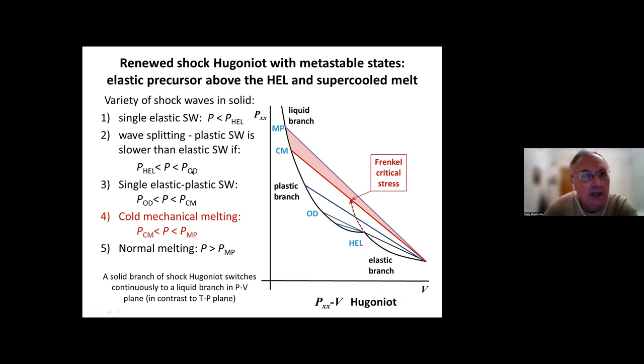So finally, I would like to show different regimes of shock wave propagation on the Hugoniot with the metastable state. What I added to this diagram, first of all, is the elastic precursor above the Hugoniot elastic limit, and also I put some region, the red area, with a formation of supercooled melt. Let's just scan what happens in a solid with increasing shock pressure. So first of all, for a very, very weak shock wave, only a single elastic wave can be observed until the pressure reaches the Hugoniot elastic limit.